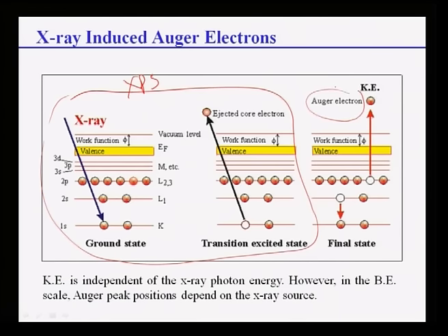You know in EDS, many other factors are dumped in. In EDX there are factors like atomic number difference and fluorescence, all dumped into a particular parameter. In the same way K has all the other factors. So frankly speaking, intensity depends on the concentration of the element, the photoelectron cross section of the element, and the inelastic mean free path of the photoelectron. These three factors. K is normally constant for any experiment. So if this is measurable and you know these two parameters, we can calculate Ni. That is how the quantification is done.